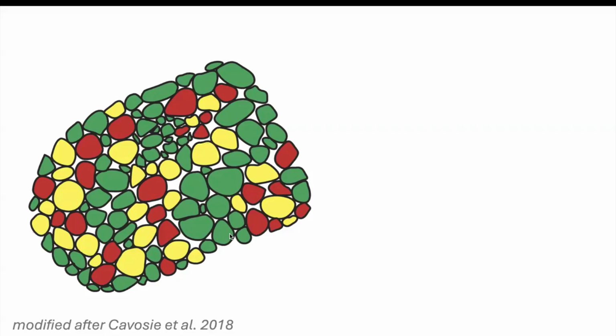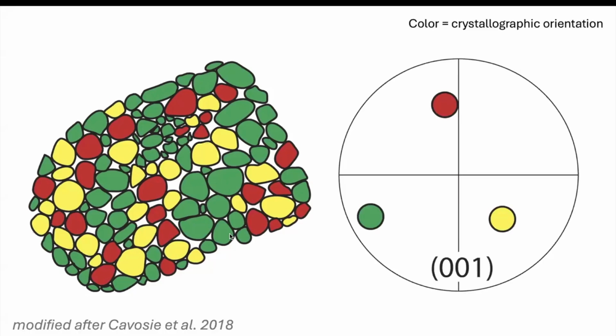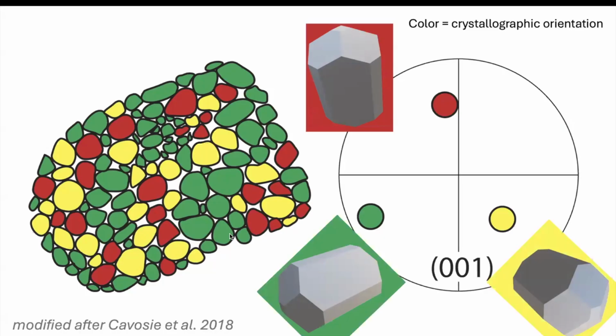So here's a cartoon of a systematically oriented granular zircon. If we plot these orientations on a stereographic projection, we can see that the 001, which is the long C-axis of the zircon for each granule, they're all mutually orthogonal. They're all at 90 degrees to each other in 3 dimensions. This is also true for their 110 faces. Those are the skinny edges on here. Systematically oriented granular zircons are identified by electron backscatter diffraction, which maps the crystallographic orientations of each pixel.